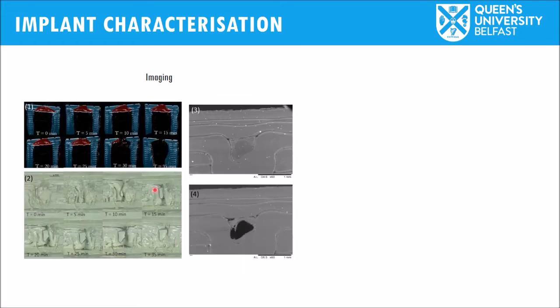Additionally, we studied the dissolution of these PVA windows as a function of time, and we even used optical coherence tomography to evaluate the dissolution in PBS, not water, in an aqueous environment. The dissolution of these windows was quite fast. In 35 minutes we can see that the windows dissolved completely. Obviously, in biological tissue, the availability of fluid and the diffusion of the polyvinyl alcohol will be slower, but we anticipate that it will happen quite fast, and the drug will be allowed to permeate and be released from this aperture.